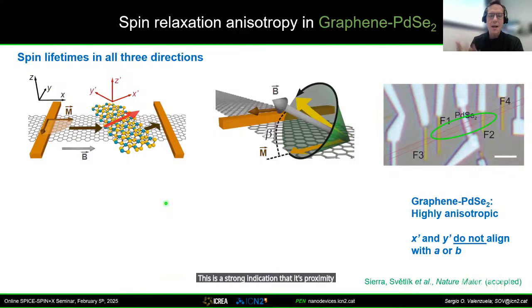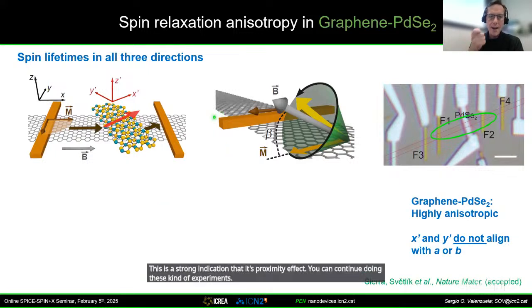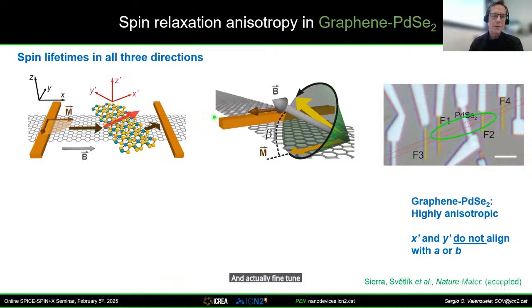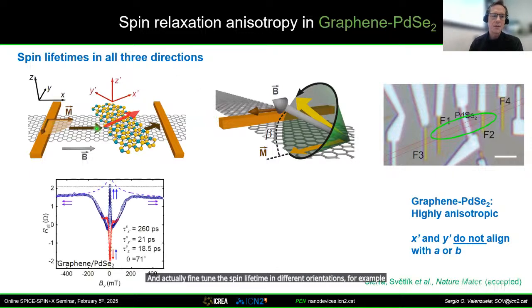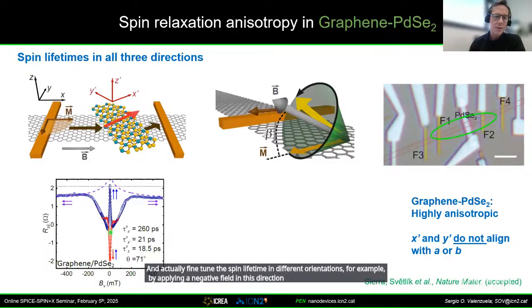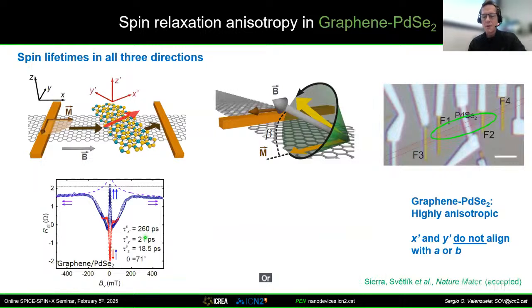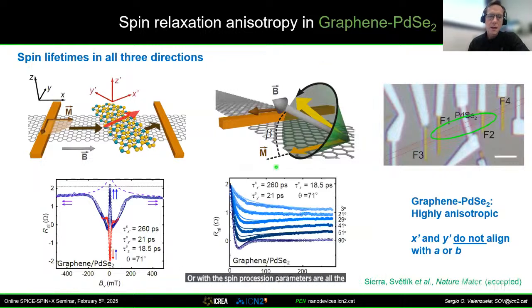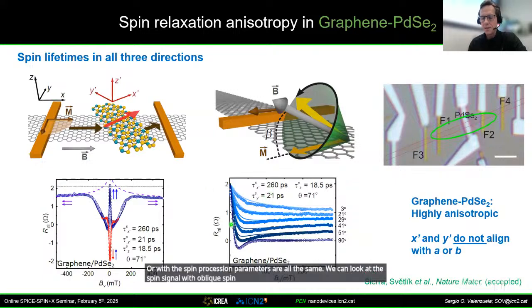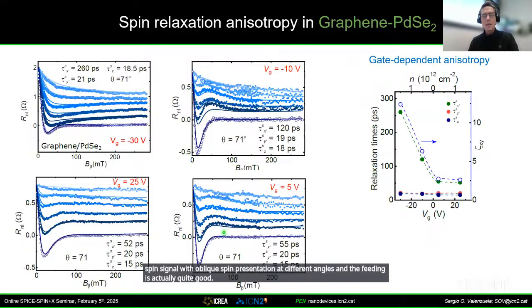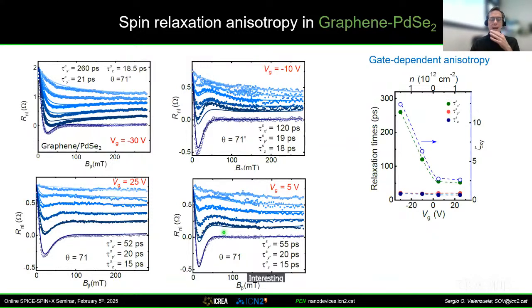You can continue doing these kinds of experiments and actually fine-tune the spin lifetime in different orientations. For example, by applying a magnetic field in this direction, we can use the same parameters and look at all of the little details for the magnetization aligned with the magnetic field here or with the spin precession. Parameters are all the same. We can look at the spin signal with oblique spin precession at different angles, and the fitting is actually quite good. An interesting result also is that these results are tunable.